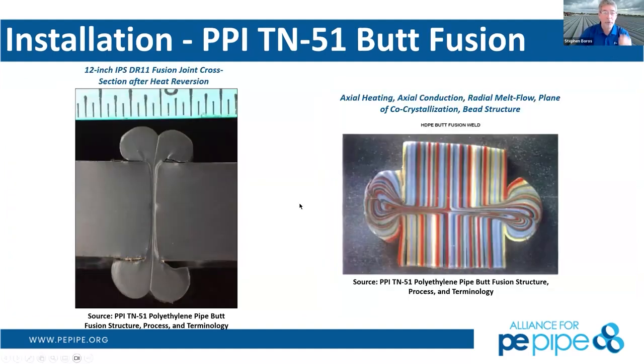This is what happens during a butt fusion joint. So you can see here, this is the wall thickness. You can see the two ends were brought together, and it talks about the different aspects of it. So you get your external rollback bead and you get your internal rollback bead from the molten material that was squeezed out. And it gives you different flow profiles. You can see on the picture to the right here, which was a very unique piece of pipe that was made. I'm not sure if it was made on purpose or by accident, but it certainly gave a good graphic for this example. You can see that when the pipe ends are brought together in this fashion, the melt is extruded out this way, and that interface is right here in the middle, which you get that, what we call a co-crystallization zone, where you get that real entanglement that gives you a fully strong joint.